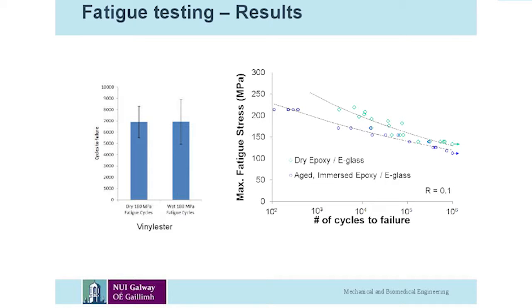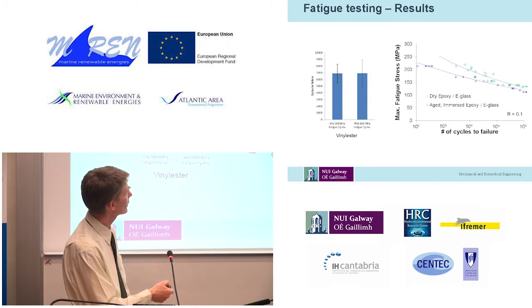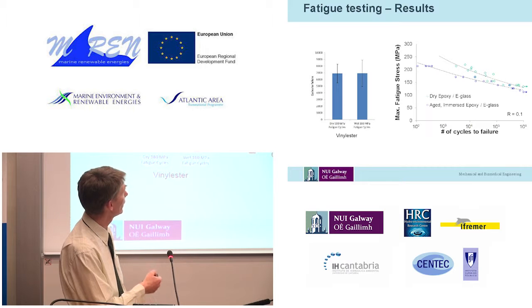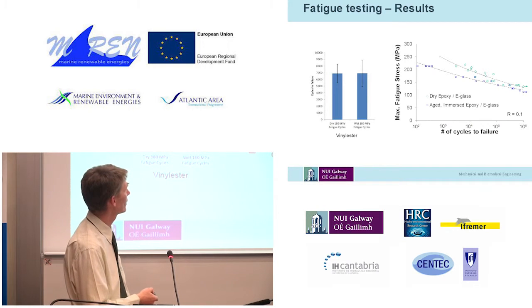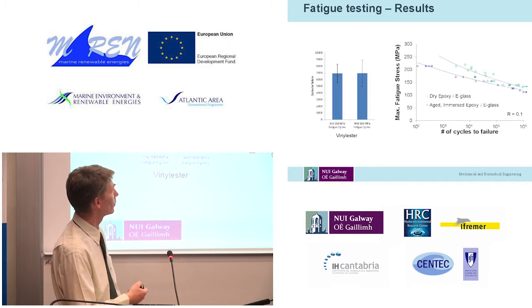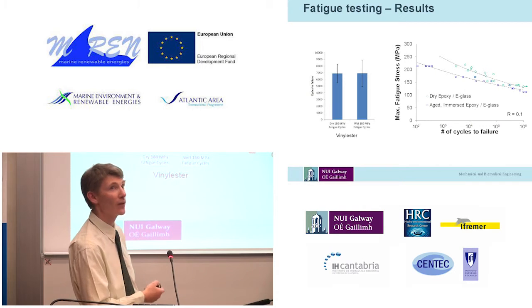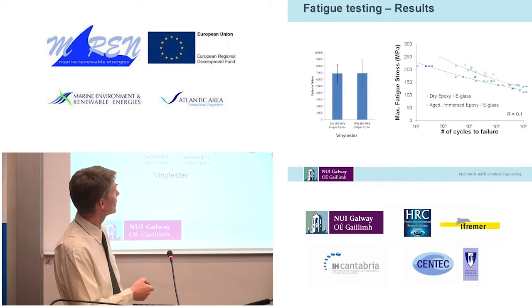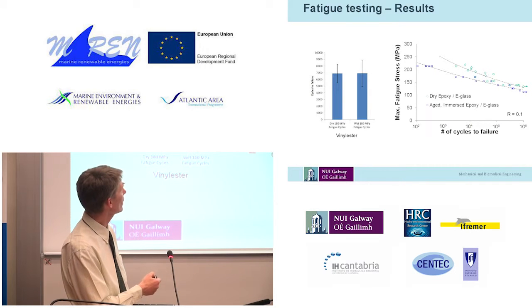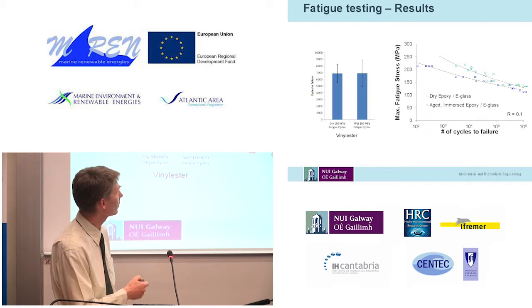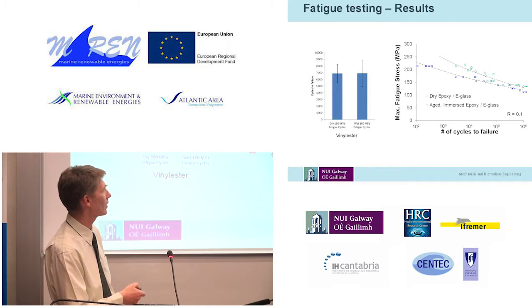So in terms of results, over here on the right there's a graph that plots the effect of the water on the epoxy E-glass. The top line here is the dry fatigue strength of the material, and right under it is the fatigue strength of the water-saturated material when it was tested after that 2-year immersion. You can see here that there's a 20 to 25% loss in strength when the material becomes saturated at the high stress end of the curve, and down here about 8% loss in strength at nearly 1 million cycles.